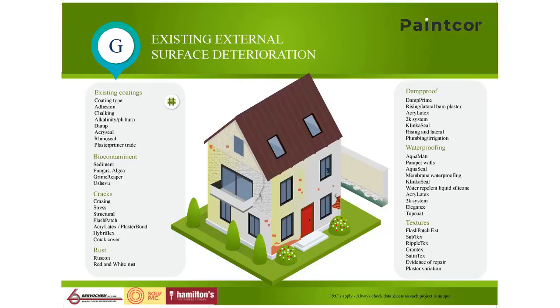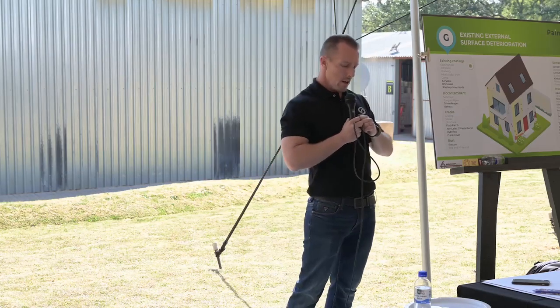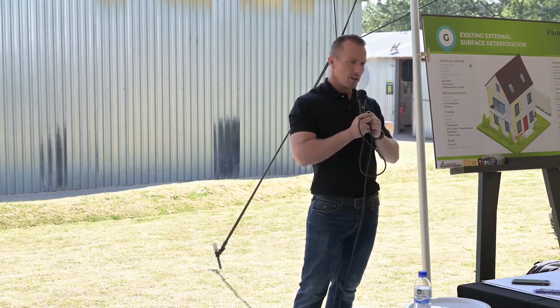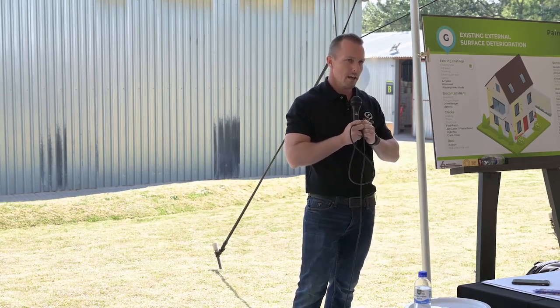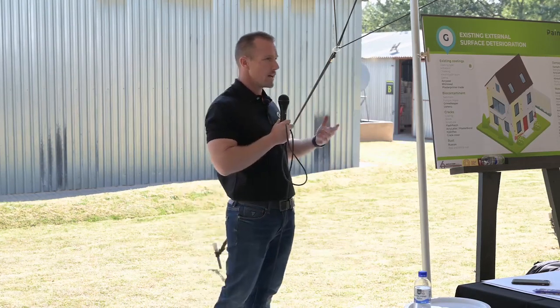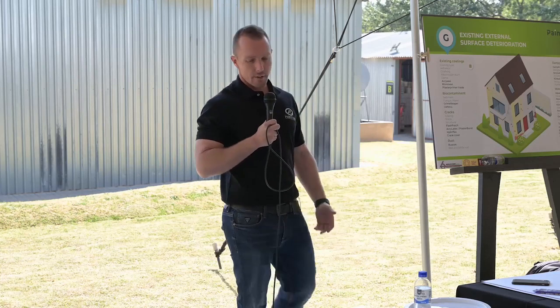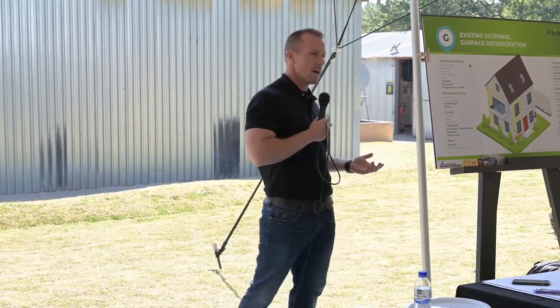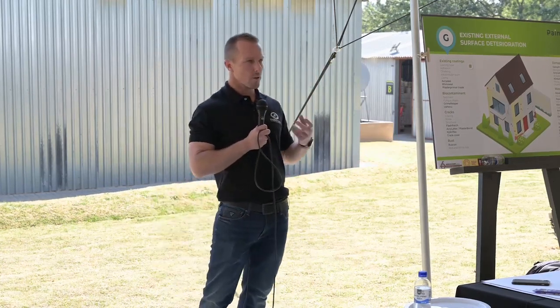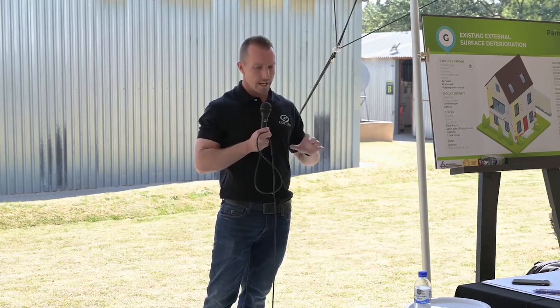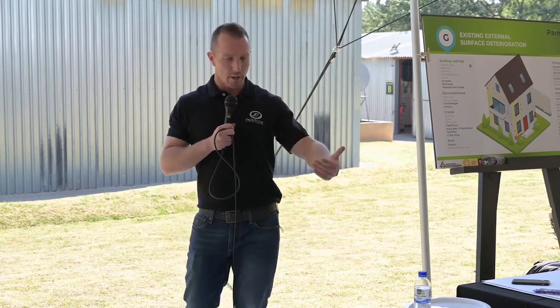Where you have slightly larger cracks, Brett referred to stress cracks. So these are cracks characterized by bigger openings in the crack itself, something bulging and splaying out in that manner. You'll also have evidence of damp around the cracks, so maybe some blistering or delaminating paint around these cracks. That is a type of crack that unfortunately would need to be exposed or opened up. To do that, you're going to use your scraper to break down the crack, remove any friable particles from within the crack, make sure that it's nice and clean before you can continue stabilizing that crack and then patching it.